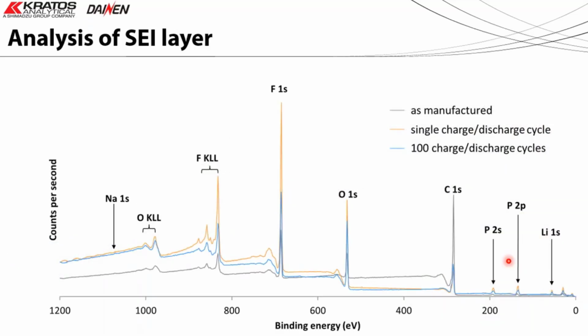So this is a survey spectrum, aluminium excited, from our 3 samples. Grey is the as manufactured, the orangey colour is the single charge discharge, and blue is 100 charge discharge cycles. And we can see what we'd probably expect. I don't think there's any real surprises. The formation of the solid electrolyte interphase layer on the lithium-ion battery has occurred, and we can look at the chemistry as that progresses through the charge-discharge cycle.